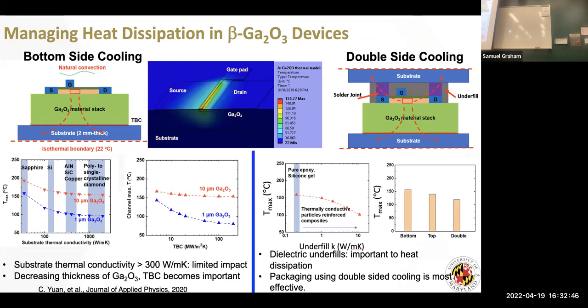The other part is this thermal boundary conductance. If I'm at 10 micron thick gallium oxide, it's relatively flat compared to if I go to 1 micron. So you can see that the thermal boundary conductance really matters when I have thin layers. Really what it's saying is that when this is really thick, this basically dominates the resistance. When I thin this, then this resistance matters. That's basically what we're saying here.